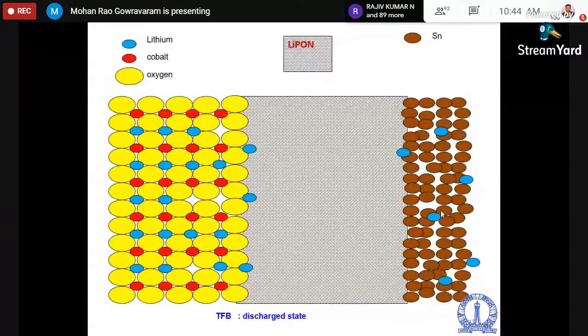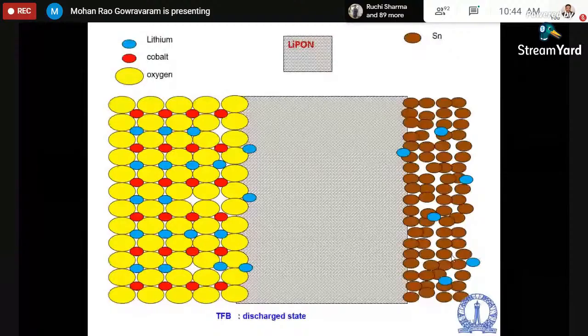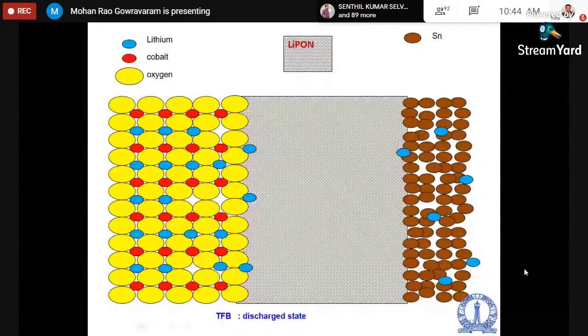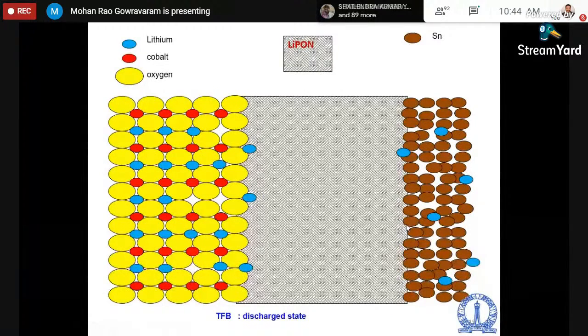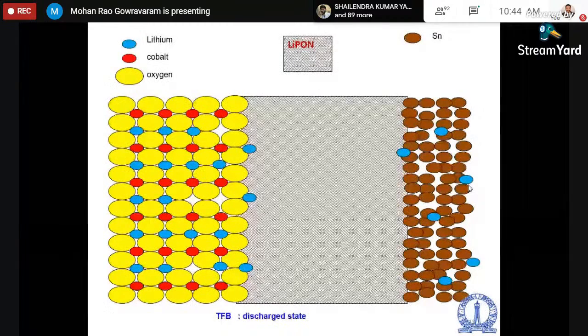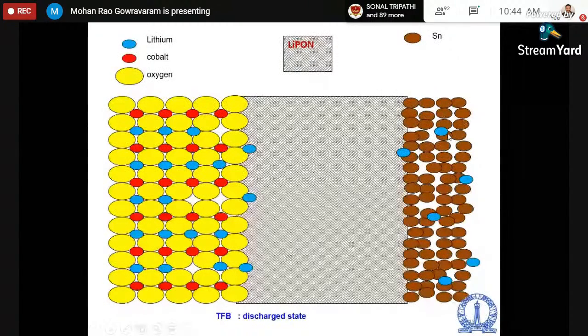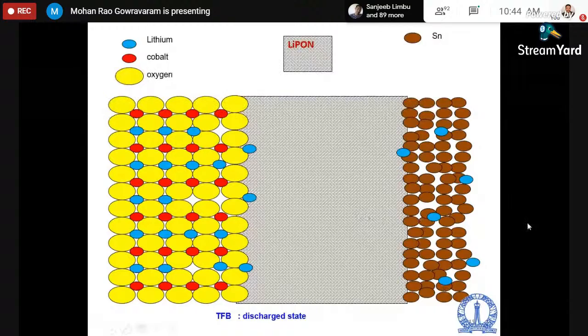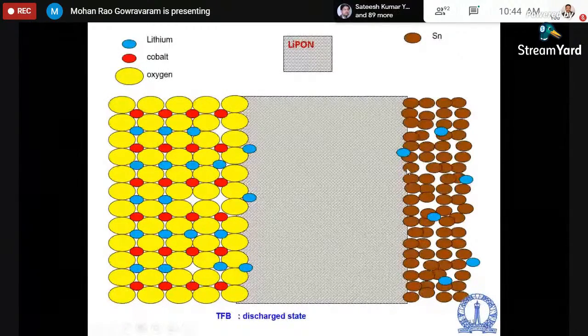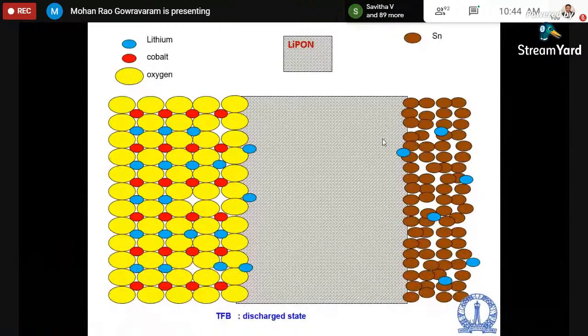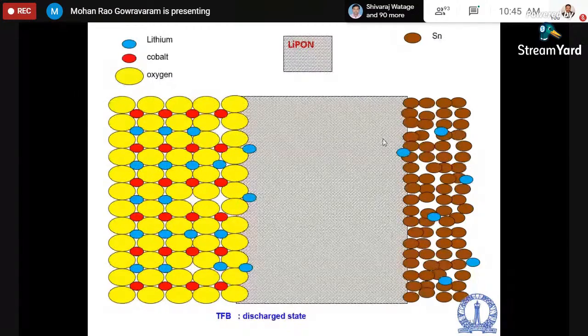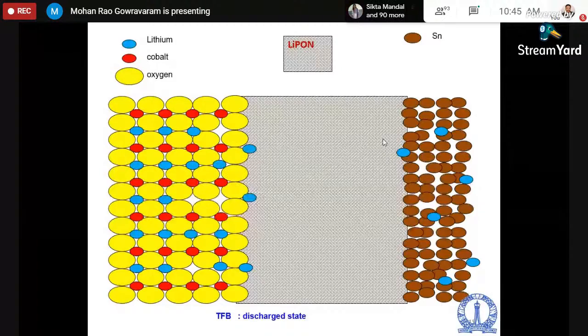Now, when you try to make a good battery, the first important aspect is that all the lithium that has gone here should migrate fully, and whatever has gone should come back. That means ideally this should be a porous structure for the anode. The second aspect is that when the lithium goes from the cathode to the anode during the charged state, there is a volume expansion that is taking place. And when deintercalation takes place, that means when it is getting discharged or when the lithium is coming back, there is a contraction that is taking place. That means during charge-discharge cycle, your battery is undergoing volume expansion and contraction. So the structural stability is very important to accommodate this volume expansion and contraction.